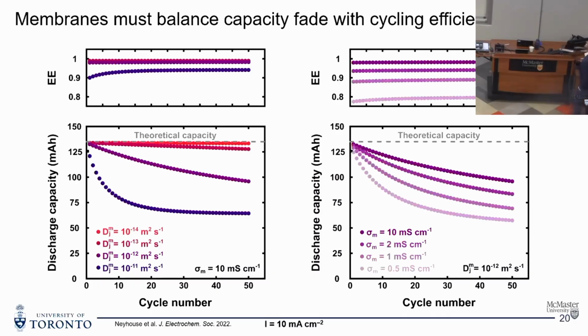And then if we vary the conductivity, we see similar changes in the performance. If we go to a lower conductivity, first off, we're going to incorporate more resistance to our cycling, so a larger energy penalty. This gives us a pretty big hit to our energy efficiency as we go to lower conductivity. But we also see an increase in our capacity fade, or just generally a drop in our capacity. What that tells us is that the conductivity is hurting us in two places. We're losing energy efficiency, and we're also failing faster. Our capacity is fading faster.